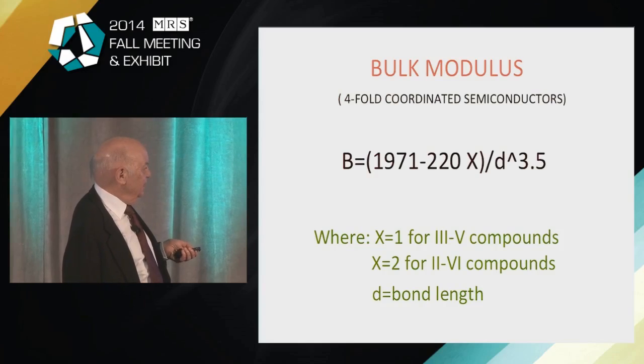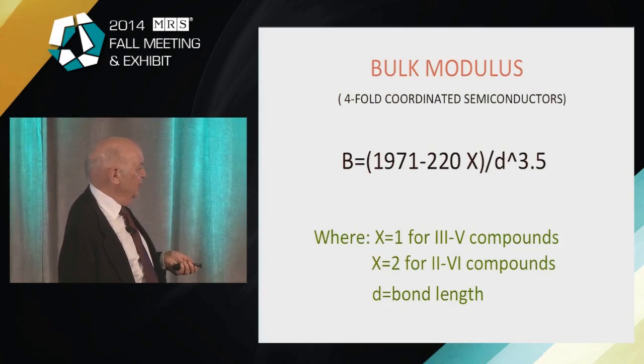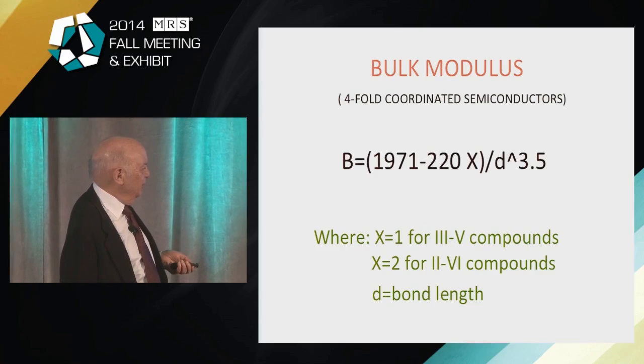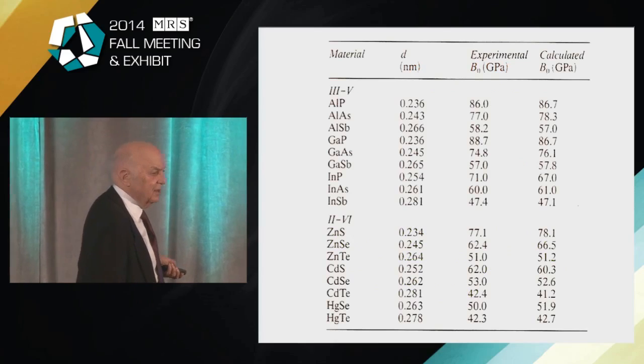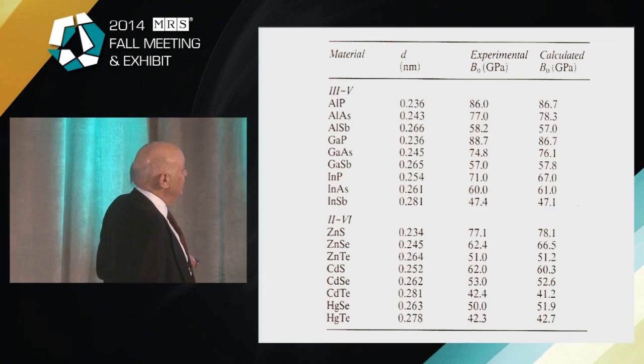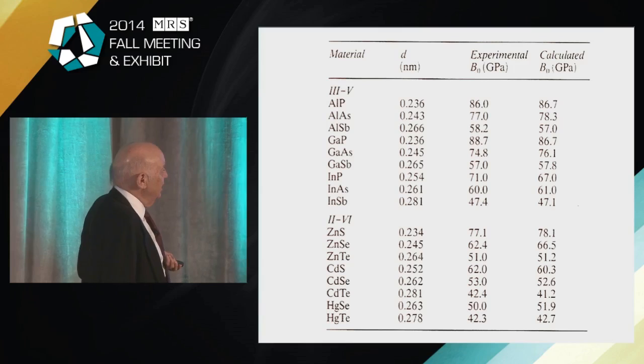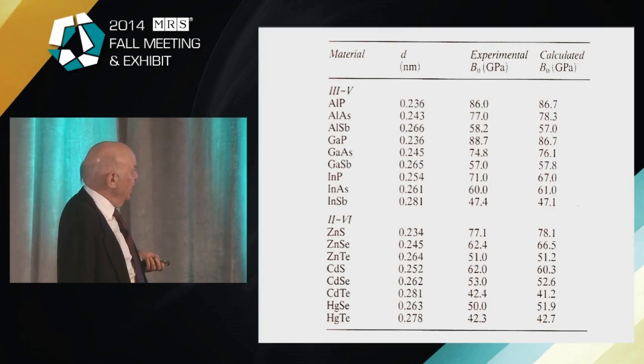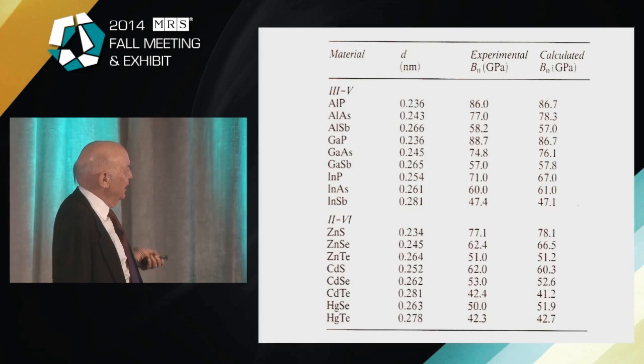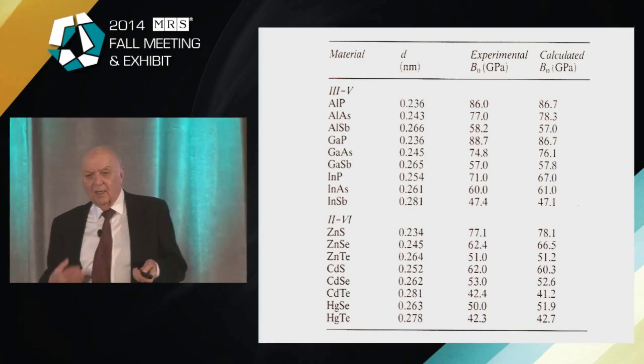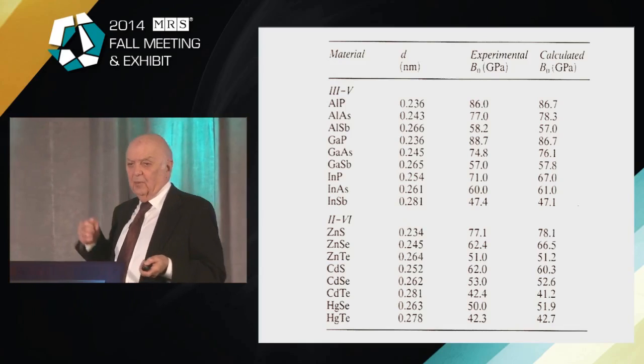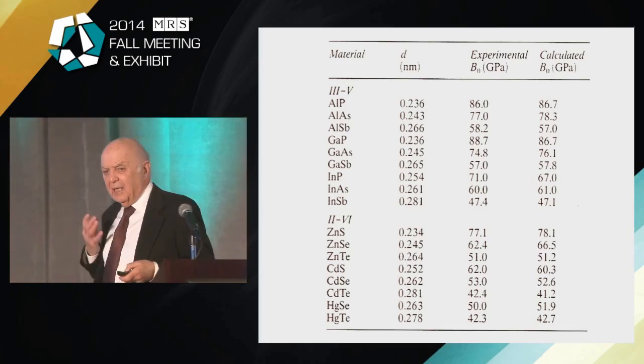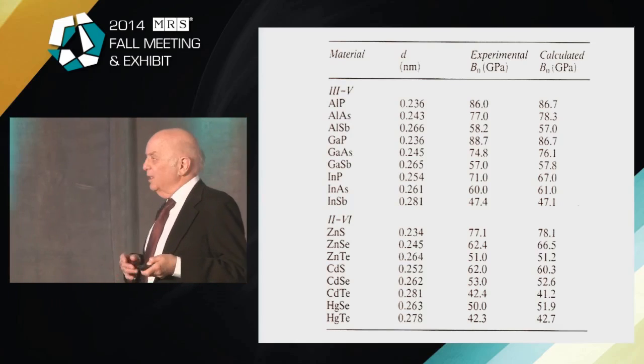The simple formula says that if you feed in the bond length between 2 atoms in there to the 3.5 power and put in x equal 1 or x equal 2 for 3,5 or 2,6 compounds, then you can explain or calculate the bulk modulus on a hand calculator for all the 3,5 and 2,6 semiconductors, and you could extend that formula to others. And basically, there's perfect agreement between that formula and experiment. So that's an empirical theory that came from optical properties that gives you an idea about the mechanical properties. So everything is hooked together.